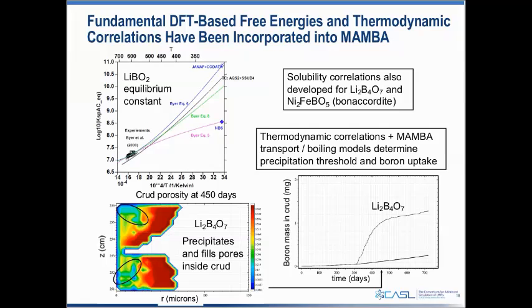You can see near the cladding surface on the left, in the Z direction, the blue and green regions represent solid phases of lithium tetraborate, where it's precipitated and filled the pores of the crud layer. So it's no longer a porosity of 0.7, it's more like a porosity of 0.2.